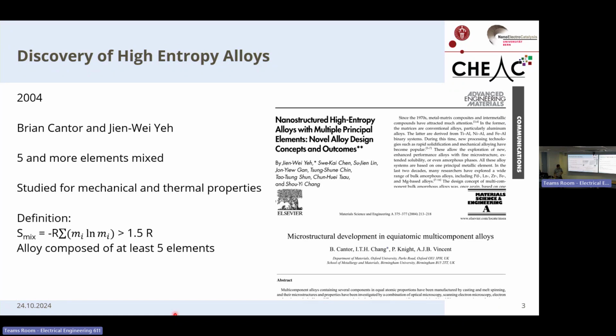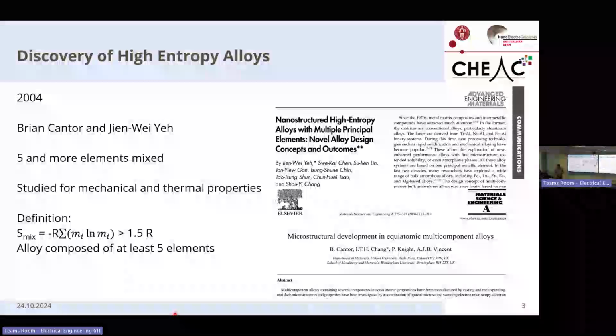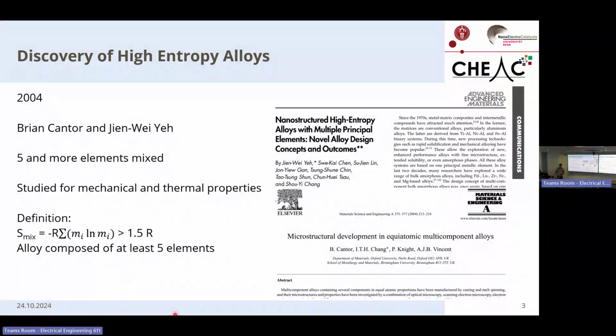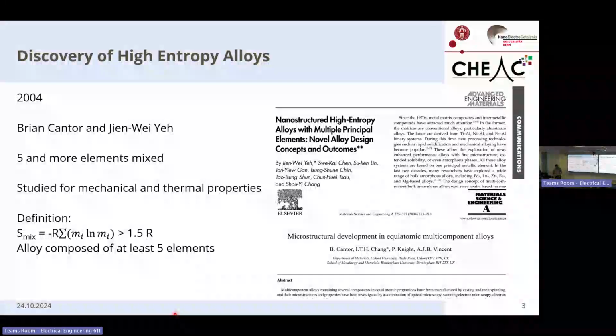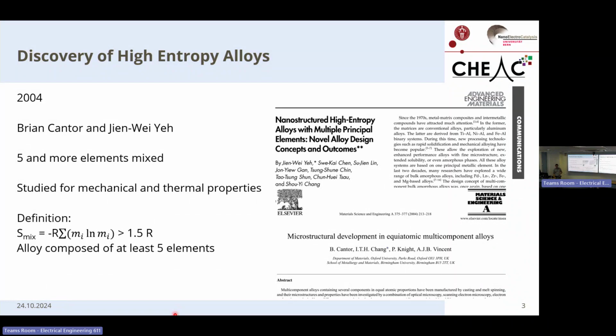And Jien-Wei Yeh defined high entropy alloys as alloys that have a mixing entropy larger than 1.5 R. And this mixing entropy is sufficiently large to rival the entropy of formation of intermetallics, and that's why they break down and create a single-phase, highly disordered structure. Commonly, this definition is also reworded as an alloy that is composed of at least 5 different elements, because that's the minimum criterion to get a mixing entropy larger than 1.5 R.